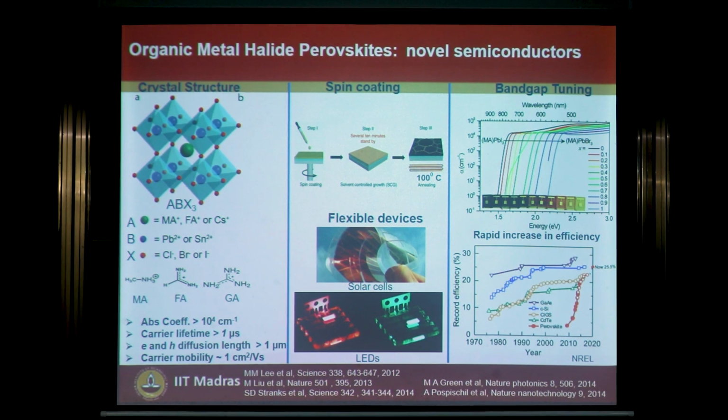For example, it's already a tri-element system like ABX3. There can be an interstitial or a vacancy. Many defects can arise. Out of them, only 4 defects are identified which are prone to very strong quenching of charges. So some of them are lead vacancy, interstitial iodine, and I'll show those, and some interstitial methylamines also.